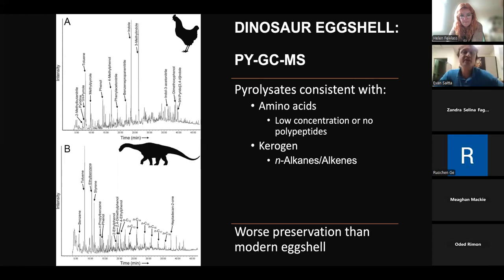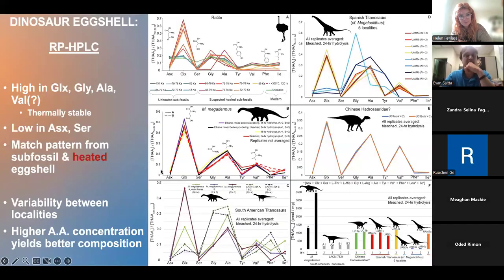So again, pyrolysis GCMS between a dinosaur eggshell and a modern chicken eggshell. What we can see is that although there are pyrolysis products that you would expect from, say, amino acids in the dinosaur eggshell, you get a smaller set than you do in the modern eggshell. This could be low concentrations of material in the dinosaur bone, or maybe less complex organic material. So instead of polypeptides, maybe more free amino acids. And we also see these alkane-alkene doublets, again consistent with this sort of organic geopolymer kerogen preserving in the eggshells, consistent with the fact that these are very, very old Mesozoic dinosaur eggshells. Overall, the preservation is not as pristine as the modern eggshell.